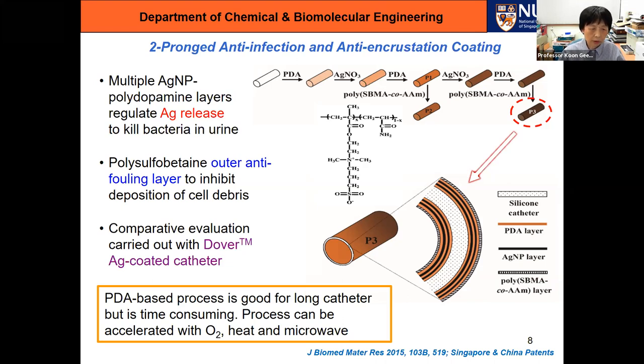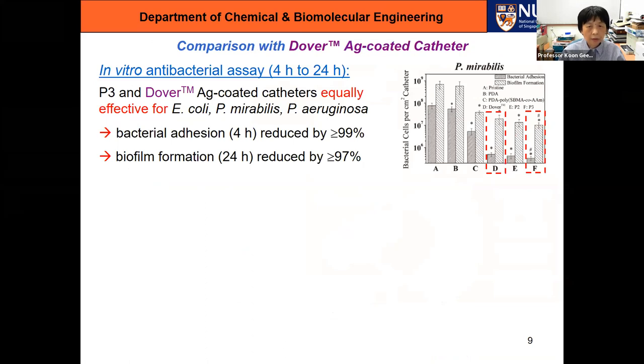silver coated catheter. So the first thing we did, of course, is just do the in vitro test. And it suffices to say that both our coating and the Dover catheter perform equally well. There's not much difference. So for bacterial adhesion within 4 hours, the number of bacteria can be reduced by 99%. And for biofilm within 24 hours, it can be reduced by 97%. But the real test comes from encrustation.